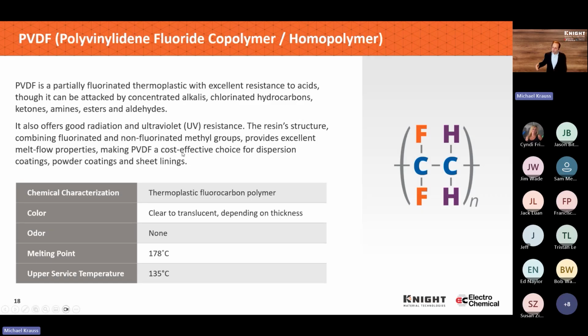Again, as we start looking at corrosion data and things to be aware of, PVDF, the homopolymer, which we're showing here, is extremely rigid. The difference in thermal expansion, the coefficient of thermal expansion between the steel structure and the lining material is significant. And then the rigidity of the homopolymer actually can lead to stress cracking from fairly gentle temperature swings. So the lined steel market years ago moved from the homopolymer to the copolymer.